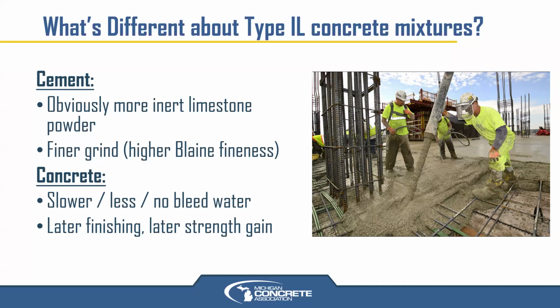But obviously, there's more limestone in it. That Type 1L, that L meaning limestone, allows more limestone. There's going to be more of that inert limestone powder interground with the clinker and the gypsum and any other grinding aids or whatever the cement companies decide or are allowed per specification to put in there. That's the biggest thing. There's more limestone powder. In doing that, there's less clinker, the actual workhorse of Portland cement, the main thing that gets us concrete, gets us strength, and that means they typically have ground these Type 1L